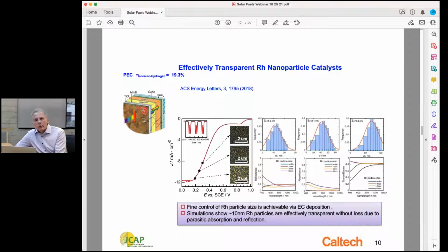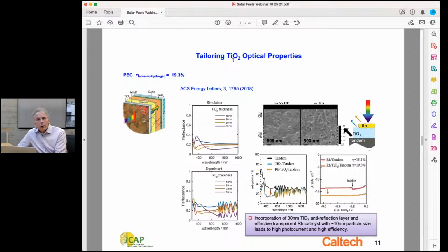In this very small size regime, where the mean particle size is between 10 and 15 nanometers, small particles have an extinction that is dominated by absorption rather than scattering. It so happens that rhodium particles exhibit a plasmon resonance in the ultraviolet, but at this particle size there is essentially negligible absorption in the visible frequency range. So this is quite interesting.